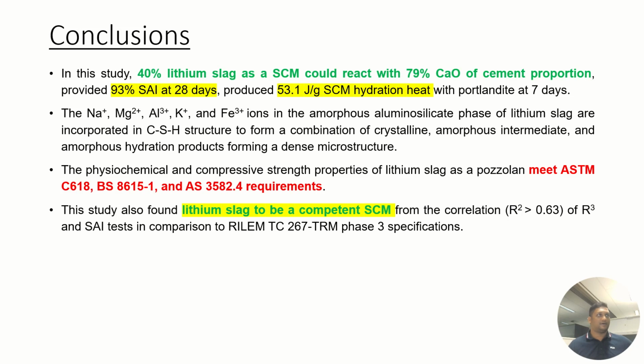In conclusion, I'd like to summarize that 40% lithium slag as a supplementary cementitious material could react with 79% calcium oxide of cement proportion and provided 93% strength activity index at 28 days and produced 53.1 joule per gram SCM hydration heat at 7 days. Also, the lithium slag provided amorphous aluminosilicate phases of hydration product by using sodium, magnesium, aluminum, potassium and iron ions in the calcium silicate hydrate structure. The physiochemical and compressive strength properties of lithium slag as a pozzolan met all the standard requirements, and lithium slag is a competent SCM, as the R square value has confirmed.